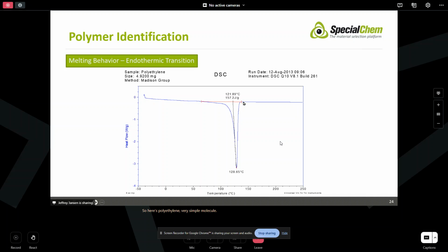And if we look at that, again, what are we looking at here as we evaluate the heating run here? We see that we've got a melting point. Now, the melting point for polymeric materials, by convention, is the maximum, well, I guess it would be the minimum of that peak, okay? That's the melting point of the material. The area underneath that curve is called the heat of fusion. So that's reported in joules per gram. And then typically there's an onset value that is also reported, although that's a little bit less used. Again, the melting point for polymeric materials is going to be that minimum on the melting endotherm, okay?